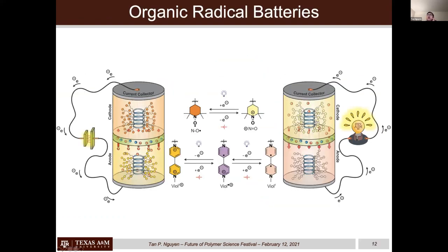Okay. So on this slide, you can see that the bipyridine here can be reduced from 2+ to 1+. So that's the first 1.1. And from this 1+ to the 0 neutral species, that's the second one. When we put them against the TEMPO, that makes it like a 1.1 and 1.64 window.